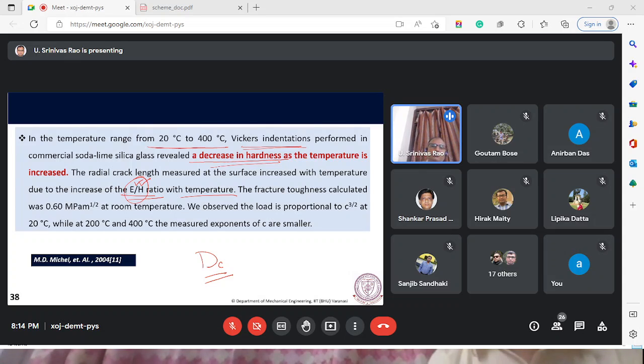Now, at the same time, E should not reduce too much. If H is reducing, E will also reduce to some extent, but both should not reduce at the same rate. So what we should finally end up with is a higher E by H.